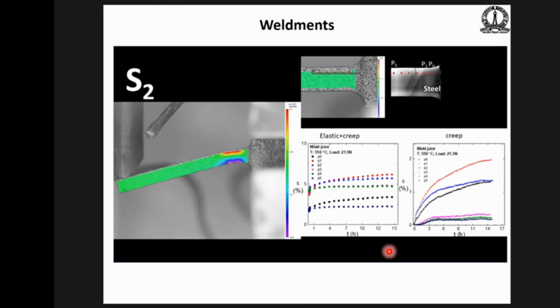And so we're now looking at welds, and these are for steam power plants in nuclear reactors, where we have a steel which is bonded to a nickel-based superalloy with a number of layers in between. There's a buttering layer, there's a weld, and so on. And so one needs to know where the failure is likely to happen, which is a sensitive region, and an estimate of what the creep rates are in that region.